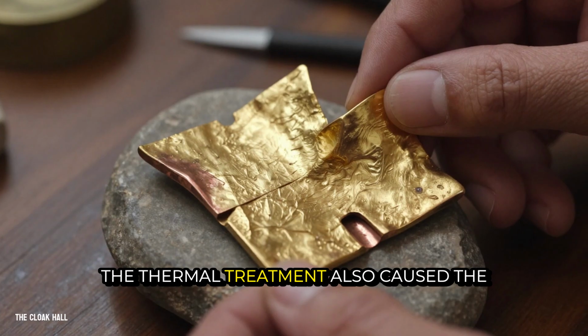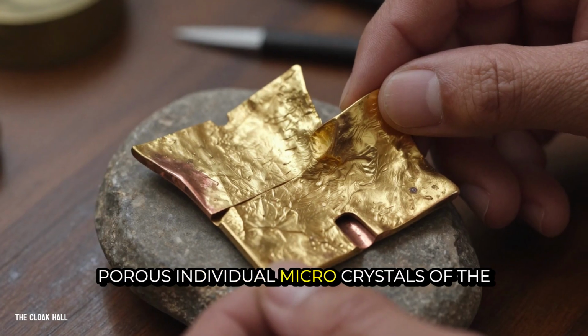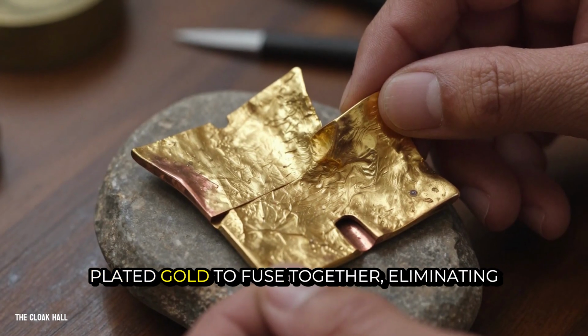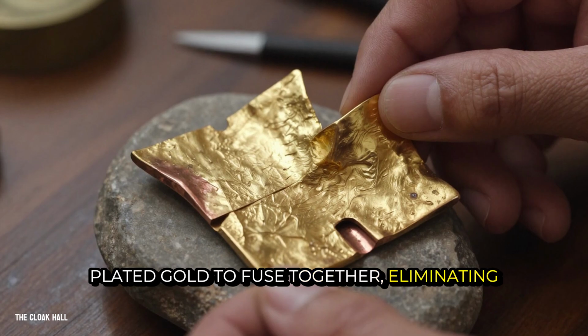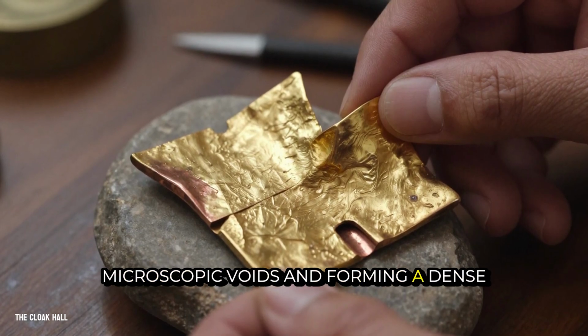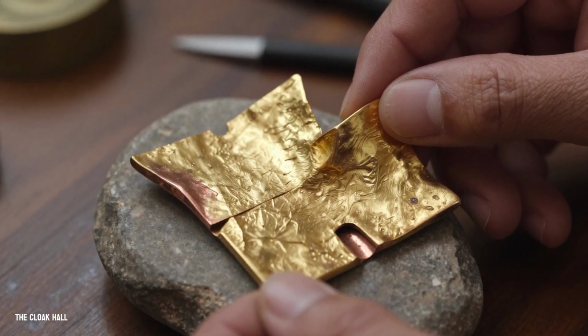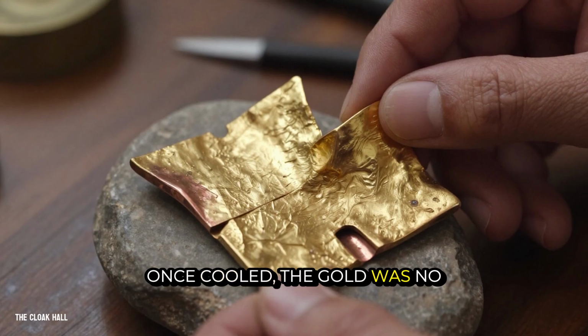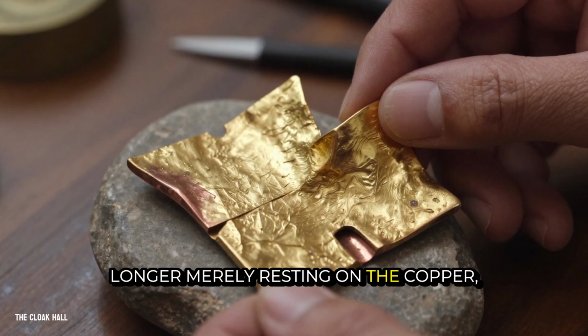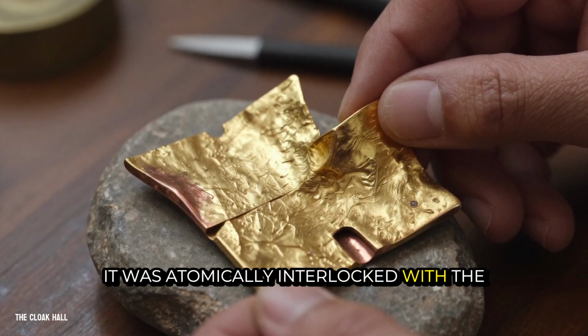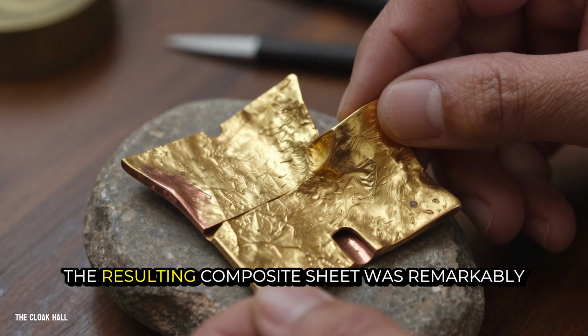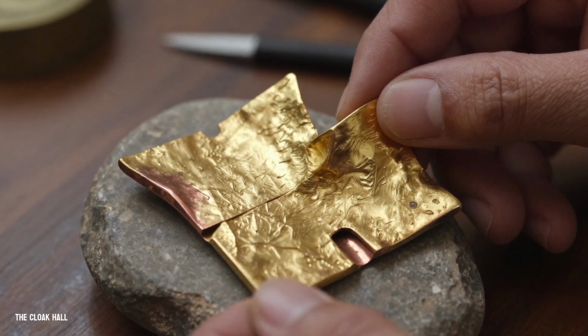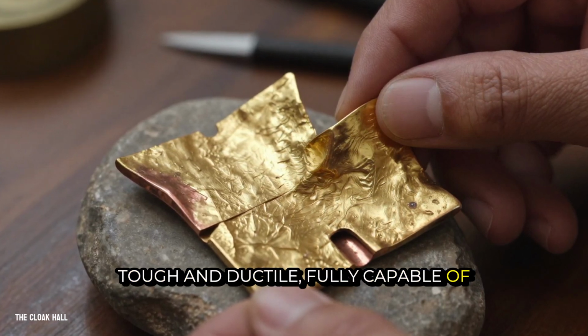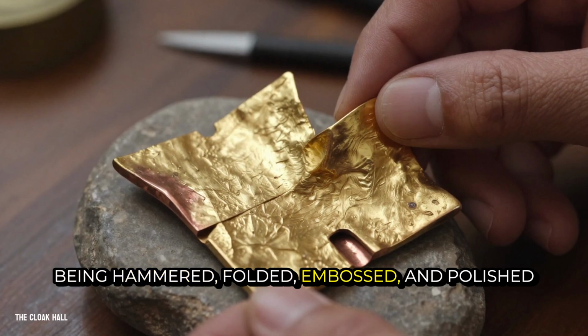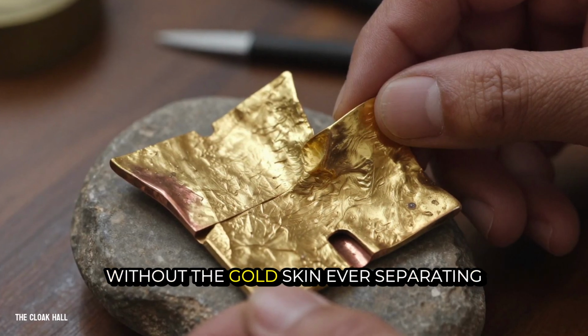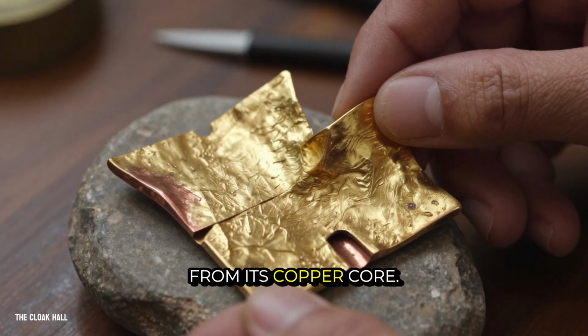The thermal treatment also caused the porous, individual microcrystals of the plated gold to fuse together, eliminating microscopic voids and forming a dense, uniform metallic skin. Once cooled, the gold was no longer merely resting on the copper. It was atomically interlocked with the substrate. The resulting composite sheet was remarkably tough and ductile, fully capable of being hammered, folded, embossed, and polished without the gold skin ever separating from its copper core.